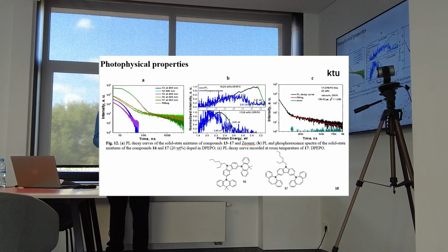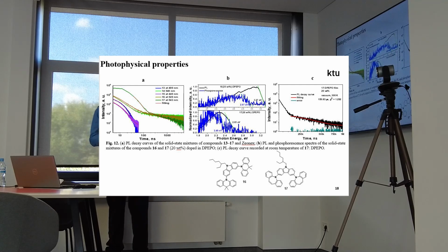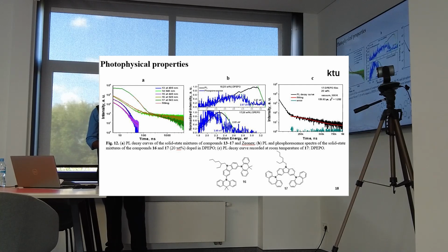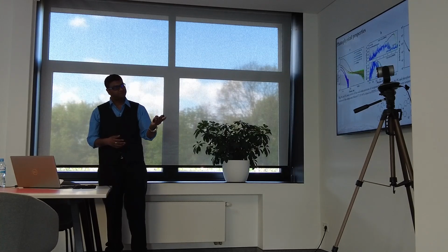Compounds 16 and 17 doped with DPEPO were used to study the phosphorescence spectra and photoluminescence decay spectra. It is revealed that in the phosphorescence spectra the triplet energy is comparatively low in comparison with previously measured tetrahydrofuran solution measurements, and the photoluminescence decay spectra revealed the longest lifetime of 159 microseconds for compound 17.